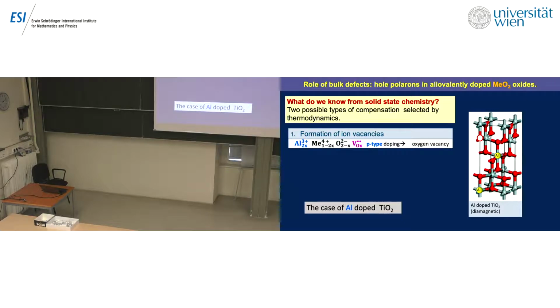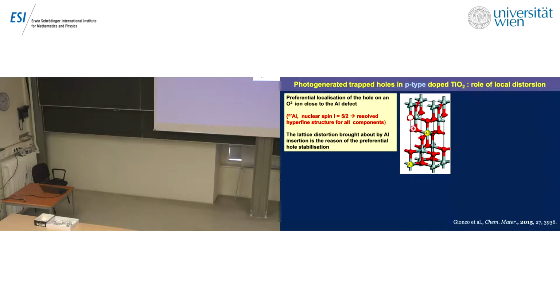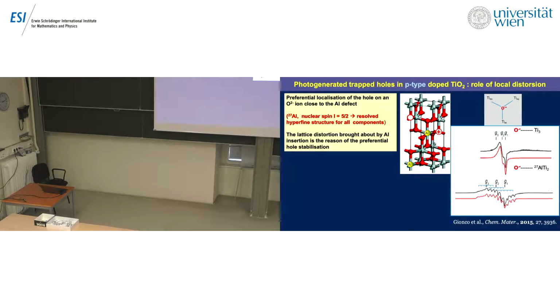Why can I say that? Because I don't see any hole. And the holes in this system are clearly visible because if we irradiate the system, okay, we can observe directly a hole, and the hole, as it is known to the people dealing with polarons, is strongly attracted by the defect. And so the hole stabilizes close to the aluminium. And this is visible by EPR because in normal titanium dioxide, fully dehydrated, you have such a spectrum. And in the case of the presence of aluminium, there is this beautiful hyperfine structure that derives from the nucleus of aluminium that has a nuclear spin of 5/2. And so there are 6 lines on each component of the tensor. So 6 lines here, 6 here, and 6 here.